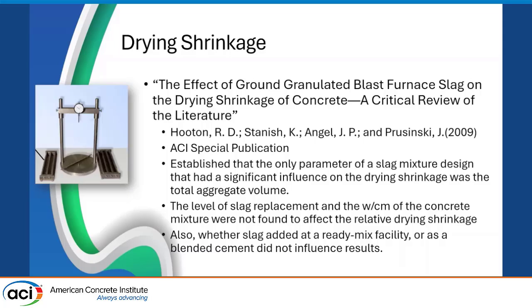The effect of ground granulated blast furnace slag on drying shrinkage of concrete, a critical review. This particular paper, there were some concerns that slag had higher shrinkage than regular Portland cement mixtures. The Slag Cement Association at the time, and I was part of it then, asked Doug to do a study on this, and he established that really the only parameter of a slag mixture design that had a significant influence on the drying shrinkage was the total aggregate volume. The slag itself, whether it's in a blended cement or added at the ready mix plant, didn't have an effect on drying shrinkage.